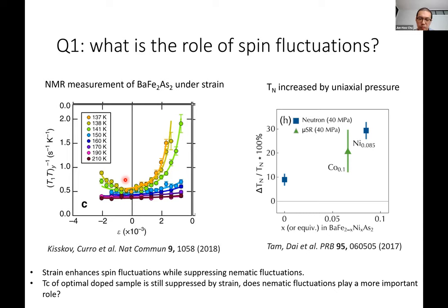No, we don't know. Basically we found that when you put strain on, the magnetic structure actually changes as well. It actually induces a c-axis moment. This is from Nick Curro's work. So this could be the reason, right? Not just the intensity matters, but also the type of the spin fluctuation really matters for superconducting pairing.